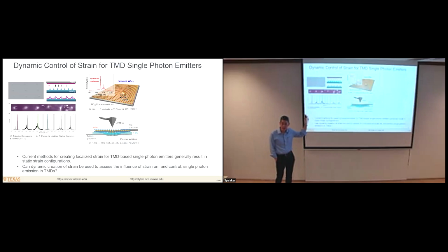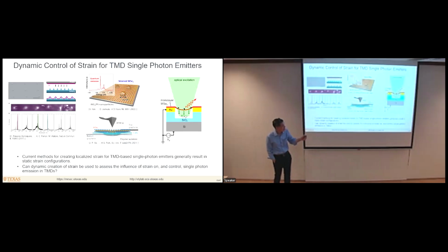Now, I'll come back to this question of single photon emission, where what we wanted to do was to see if there was some way of, instead of just having static strain distributions as shown over here, dynamically modulating the strain. And one of the approaches that we have looked at to do this is what's shown over here. We have a monolayer of, in this case, tungsten diselenide. It is suspended over a micron scale cavity, and then there's a backgate contact over here.